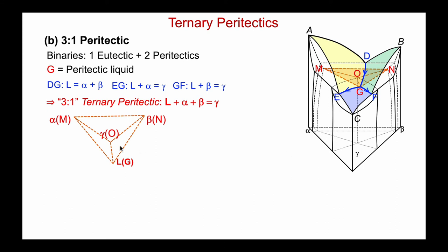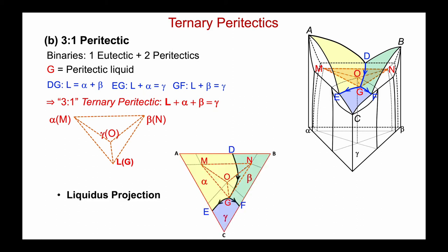Let's pull that off the diagram. This is my four-phase equilibrium representation — all coexisting together, the liquid outside the solid sub-triangle, thus a peritectic. Here's the liquidus projection: the primary phase fields alpha, beta, and gamma; the liquidus lines where I have three-phase equilibria meeting at G — the ternary peritectic. I've projected onto this the compositions of the solid phases as shown on the space diagram, so the liquidus projection contains all of the projected solid-state and liquid equilibria.